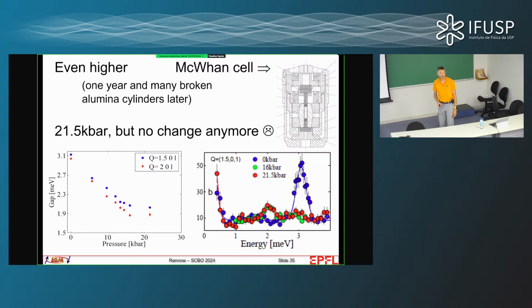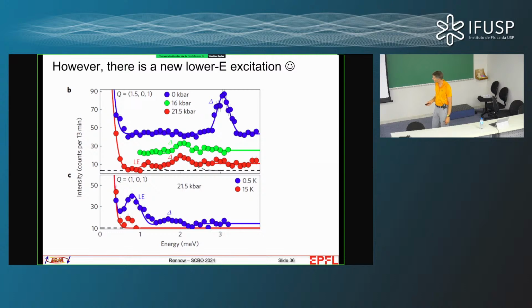It was very disappointing. It was also very puzzling, because we keep applying pressure, so why is the ratio between J prime and J not changing anymore? So that was a little bit disappointing, until when we looked more closely in the data, we saw that, okay, fine, this peak here is in the same place, but there's something new. If we track that down, essentially, in addition to this peak just below 2 milli-electron volt, there was now a new peak appearing down around 1 milli-electron volt, which was not there before.